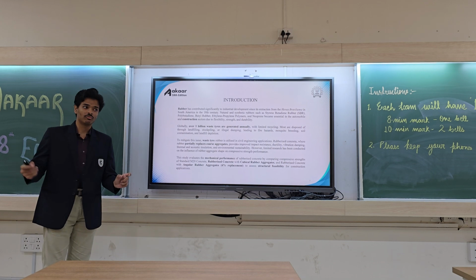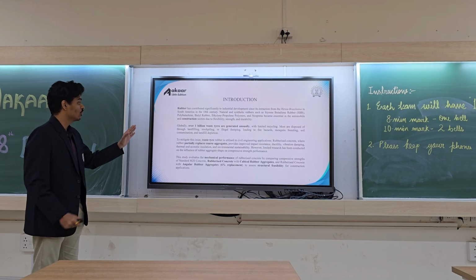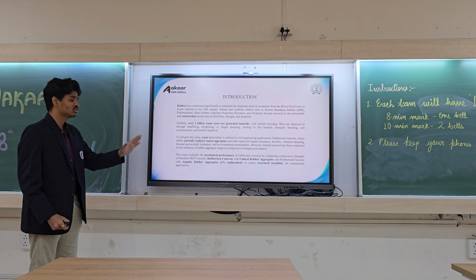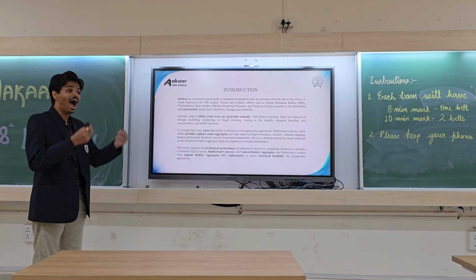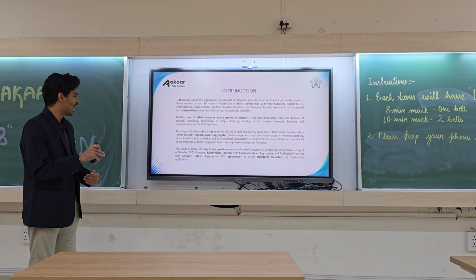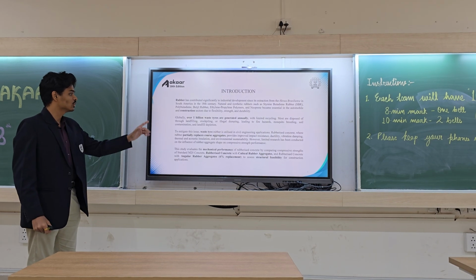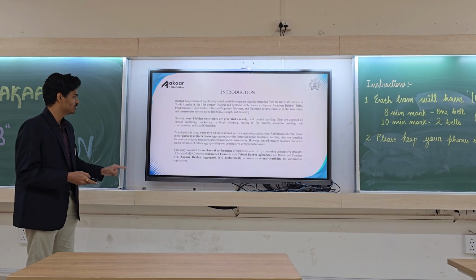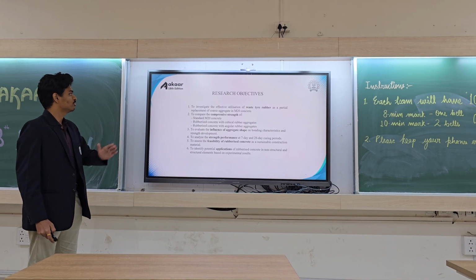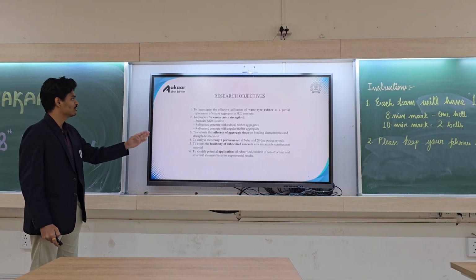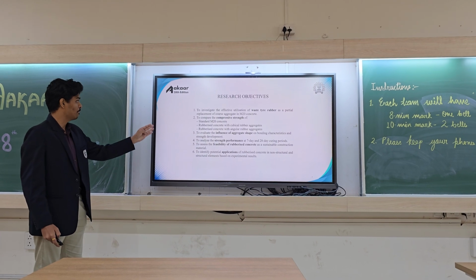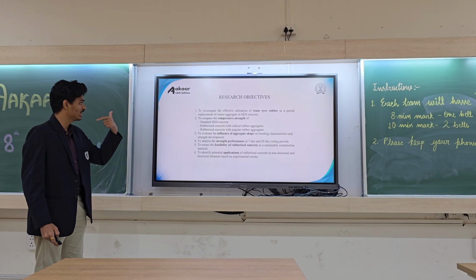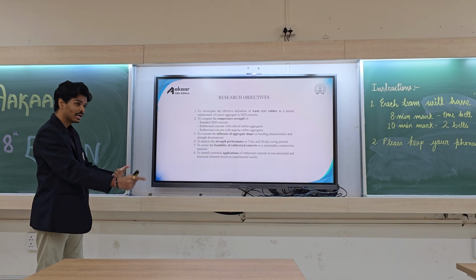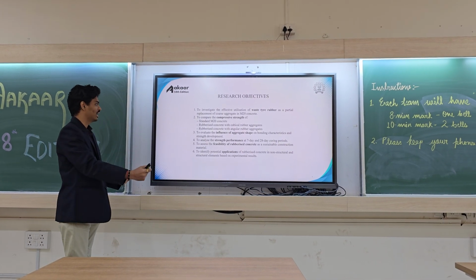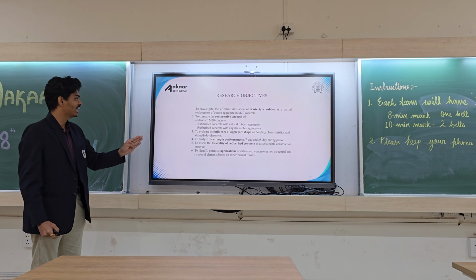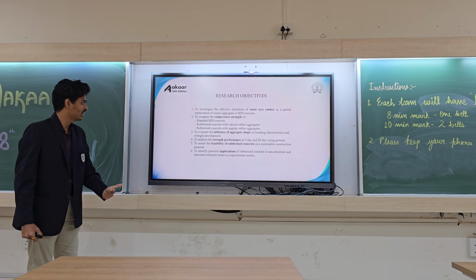But the research gap that we found was that the influence of rubber aggregate shape on concrete compressive strength performance has not been evaluated yet. Our research fills this gap by evaluating the mechanical performance of rubberized concrete by comparing compressive strength with standard M20 concrete. The research objectives are to investigate effective utilization of waste tire rubber, compare the compressive strength of standard M20 concrete, rubberized concrete with cubical rubber aggregates, and rubberized concrete with angular rubber aggregates, and evaluate the influence of aggregate shape on bonding characteristics and strength development.